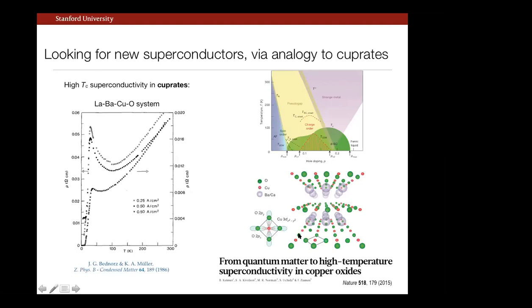I'll come back to this point later in the discussion, but namely that if I think about an isolated hole in the system, you can think of this as a system where the hole is actually coming out of the oxygen ligand field and making an overall singlet, and this is an essential constituent entity in thinking about superconductivity and normal state transport in the cuprates. And it nicely ties together this notion of having strong antiferromagnetic interactions between copper sites and how hole doping may give rise to superconductivity. This is from a review article a few years ago, the so-called Gang of 5 paper, that is well known, I think, to you.